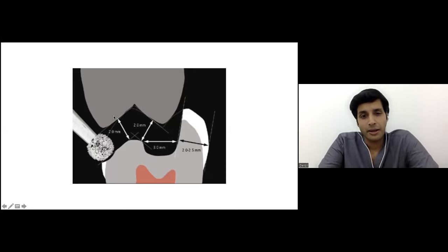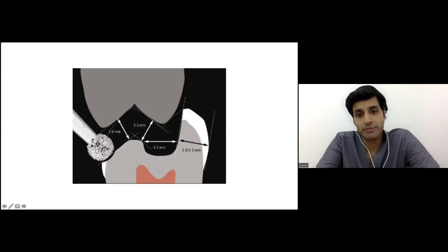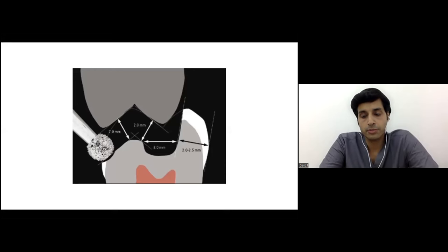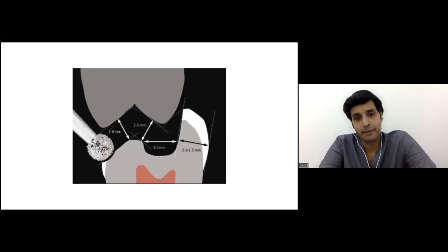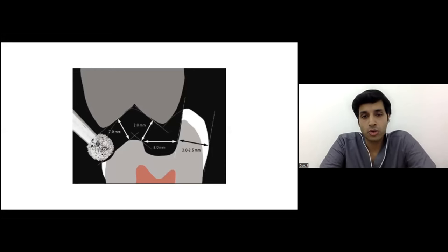from all aspects, at least 1.5 millimeters, because the restoration of choice in indirect restorations in ceramics is Emax. And there are studies showing that 1 millimeter could be enough, but 1.5 mm is a good clinical principle to go by, because sometimes on reduction, after cementation, there could be high points. So we don't want to go any thinner than that.